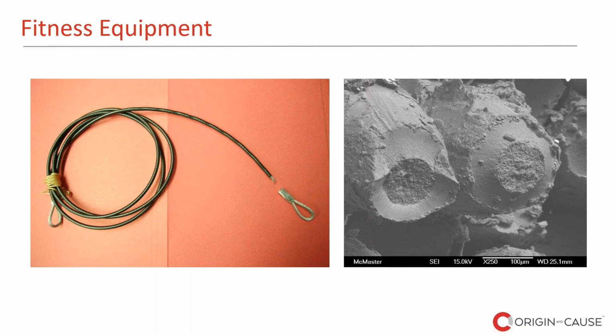This steel cable that you see on the left side image was associated with heavy lifting fitness equipment. And a gentleman using the equipment got hurt when the steel cable broke. As you can see on the left side image, it broke. Again, we put the parties together and we organized the joint destructive examination. And again, we took the fracture surface to be analyzed under a scanning electron microscope. And you can see on the right side image, these are the features that we observed.